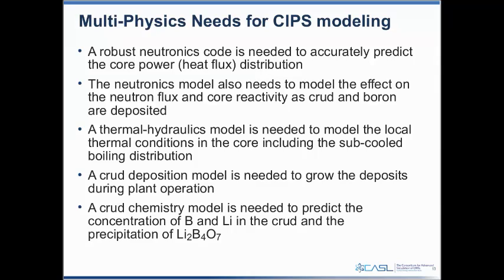We're using a robust neutronics code to accurately predict the core power distribution and heat flux. That neutronics model also has to account for the fact that we deposit crud and boron in the upper spans of the core, so we want to model the neutron absorbing effects of both crud and boron in that neutronics model as well.